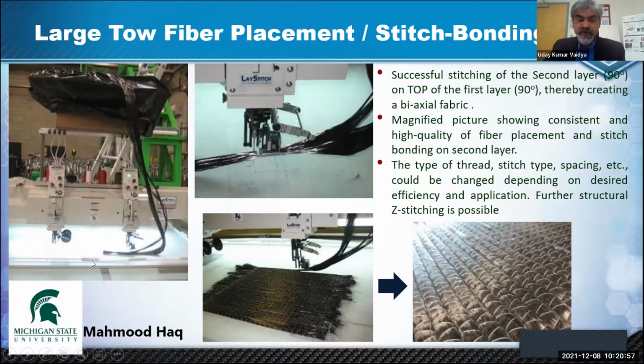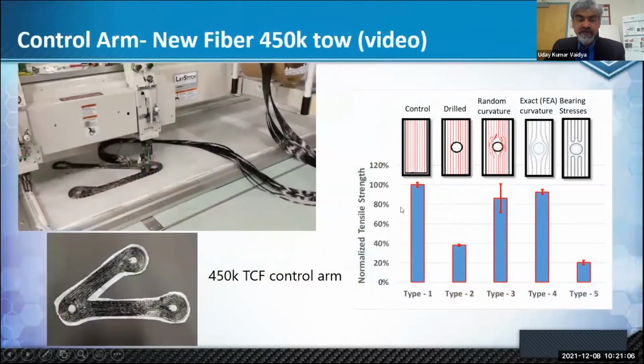So this was in collaboration with Michigan State, where the textile grade fiber has been converted to these LayStitch preforms. And then here's an example of an automotive control arm. By doing controlled stitching, you can almost see that, if this was the tensile strength of a coupon without a hole, with the proper stitching and even with the hole, you can almost get back your original properties.